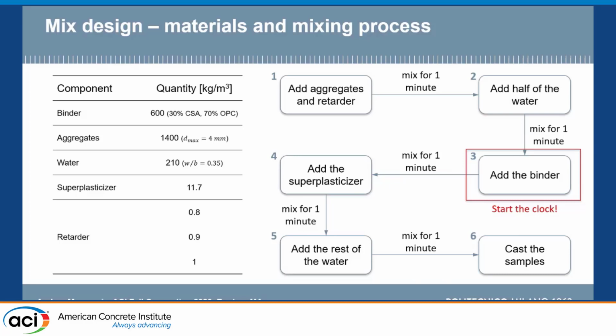So at the end of the day, we have three different mixes, and this was useful to understand the effect of the retarder in delaying the setting time, so the time at which we want to move the mold to slip and to extrude the segments. And this is the mixing procedure. We first add the powders like aggregates and retardant, then we wet the aggregates, after which we add the binder, and at this time the clock starts.